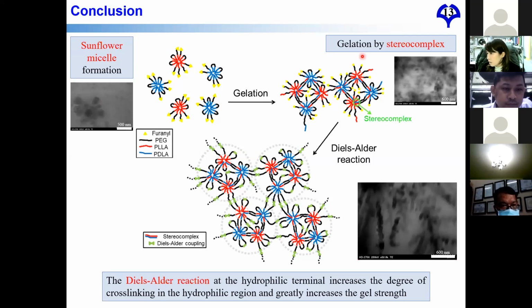And also after the gelation, after we mix the PLA and PDLA sunflower type micelle, you can see that it can be gelation by the stereocomplex, and the TEM result also shows that the micelles are linked together. The micelles are linked to each other. And then after the Diels-Alder reaction, it is only linked with the hydrophilic segment. So you can see in the TEM result that the micelles can be linked together to form a very big network in the hydrogel.